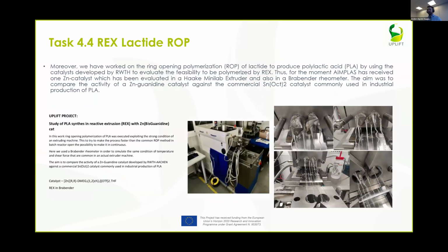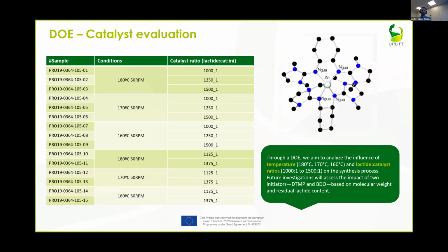Finally, I just want to touch on the reactive extrusion of the lactide part, where these new Zn catalysts from Aachen were tested in collaboration with AIMPLAS, where they looked into ring opening polymerization of the lactide under continuous conditions, doing tests to see what kind of limitations are present. This took place through design of experiment studies, where a range of different combinations of conditions were evaluated, looking into the highest efficiency of the catalyst, but also the optimal polymerization conditions for these systems.